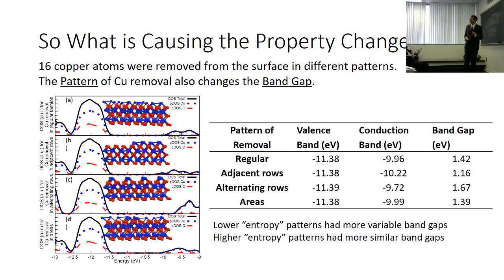So this might address a few mysteries. One, why are all the untreated samples different? Well, because in the kinetically trapped state, your band gap can vary a lot. Second, the untreated sample will have more oxygen but a lower band gap. Well, it varies a lot. It could be below what we wanted, what we thought we would have.